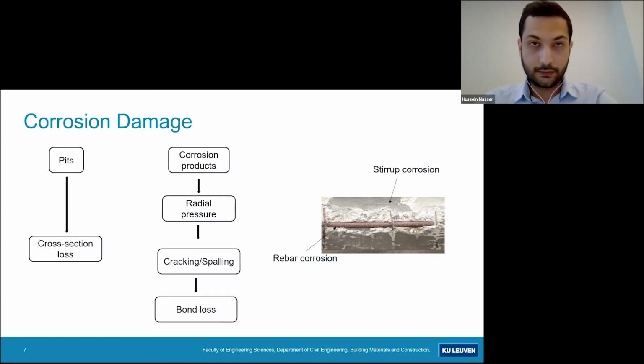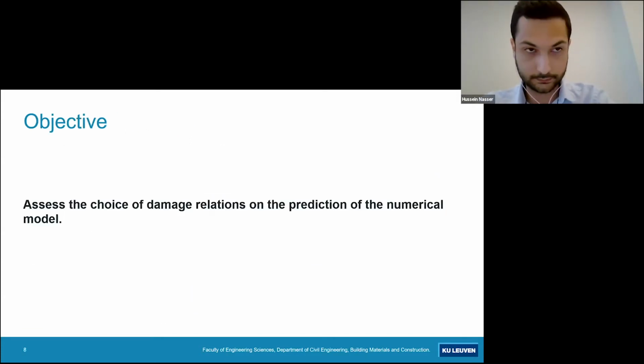This process also deteriorates the steel-concrete interface, leading to bond loss. Therefore, it is important to take into account the damage related to cross-section loss and bond loss in order to be able to predict the structural capacity of corroded reinforced concrete beams. So the objective of the following presentation is to assess the choice of damage relations related to both the cross-section loss and the bond behavior on the prediction of a numerical model, which will be validated on experimental results.